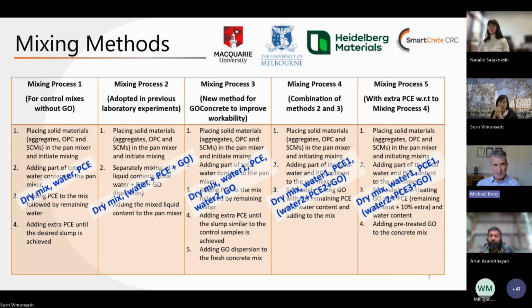So this is just a slide on the different mixing methods. It basically demonstrates the different methods that were tried, and mixing process 5, where you allow some of the concrete admixture, the high range water reducer, to be taken by the cement and some of it to be taken by the graphene oxide. But again, a lot of it will come down to what dispersion agent is used.